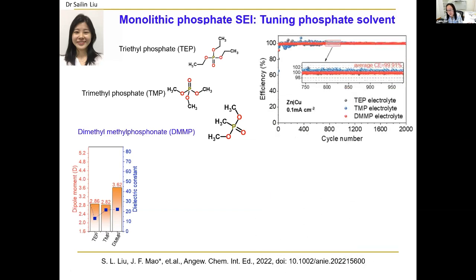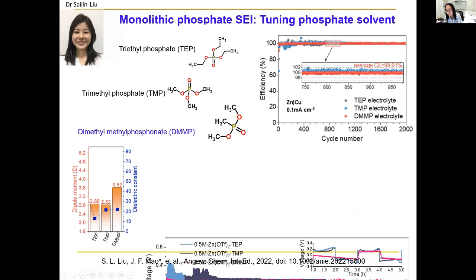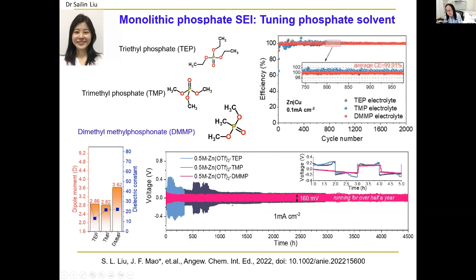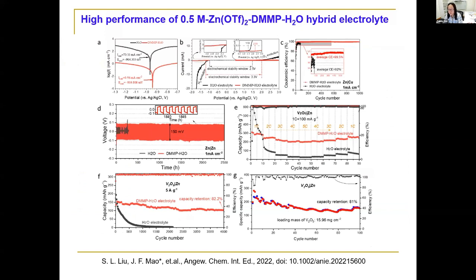So then she used DMMP as a solvent, dissolved the zinc salt to form the electrolyte, then tested the zinc-copper asymmetric cell. Using this electrolyte, it can achieve an average coulombic efficiency of 99.91%. This is very good. And the zinc symmetric cell in the DMMP electrolyte can run for more than half a year and still keep very good reversibility. However, she found the pure DMMP electrolyte seems not friendly with the cathode because the ionic conductivity is not good. So in order to boost the cathode performance, she added 10% water and formed a hybrid electrolyte. And found this hybrid electrolyte still works well.